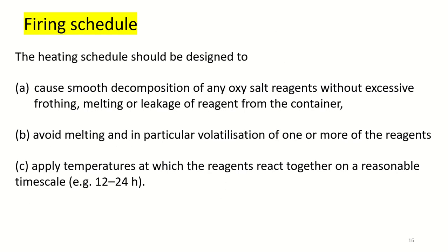The fourth one is the firing schedule. A, the heating schedule should be designed to cause smooth decomposition of any oxysalt reagents without excessive frothing, melting, or leakage of the reagent from the container.